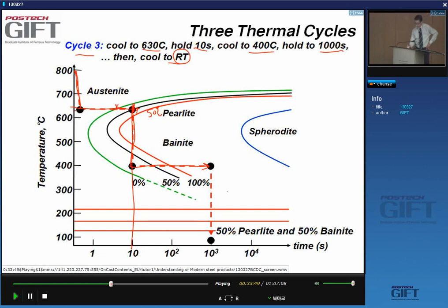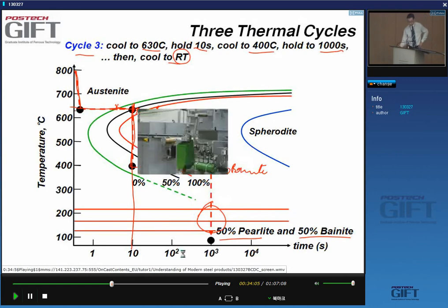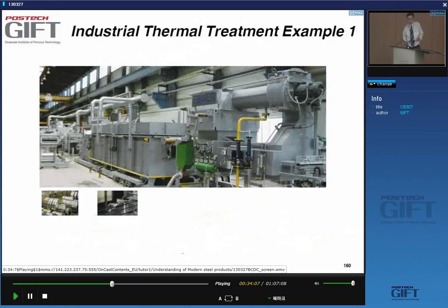So here I create 50% bainite. So 50% pearlite and 50% bainite is what we get. Note that nothing happens when I cross the MS and MF temperature because everything has been transformed. All right. So you would say, of course, or think that perhaps this kind of thermal cycle